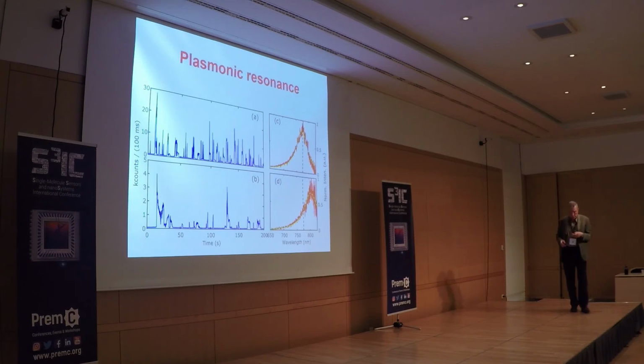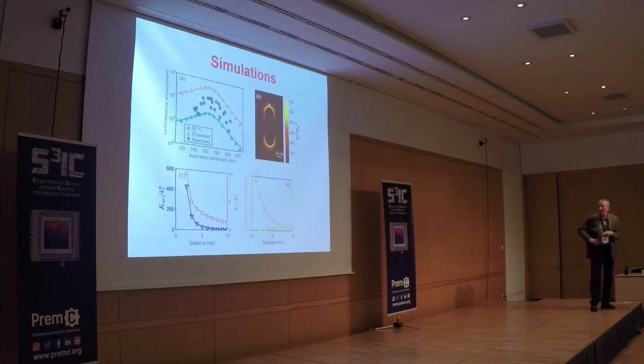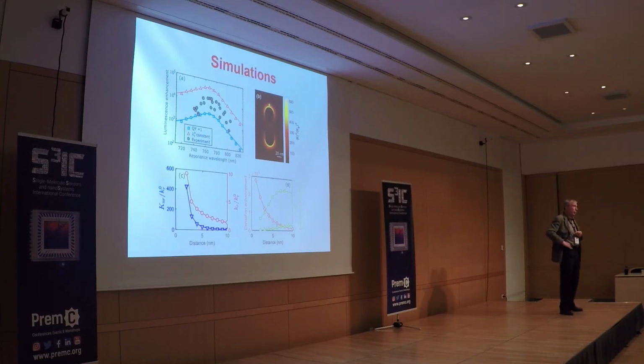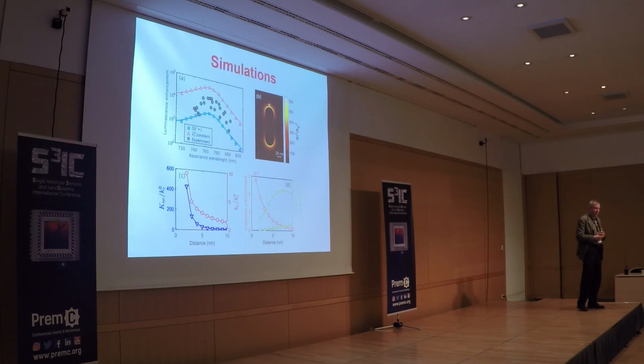So this works. We can do that, and we can also do simulations and check that this is indeed what we expect. So this is the simulation. The problem with the dot is a bit more complicated than the molecule. In a molecule, you have an excited state and one lifetime. It's very simple. In quantum dots, it's more complicated. You have several states, and the lifetime is actually a composition of different states with different lifetimes. And we don't have for every single quantum dot the exact value of all these lifetimes.